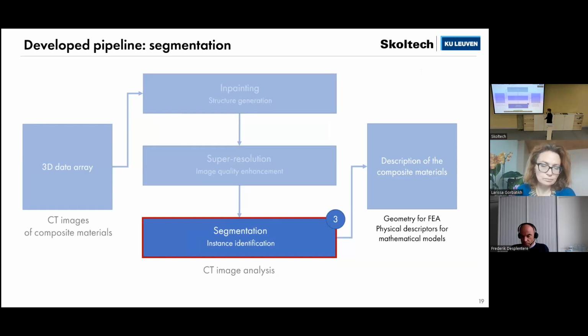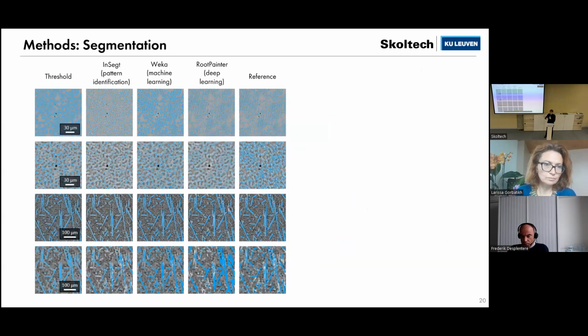The segmentation. The segmentation allows us to identify all the objects we want in our images, and here we analyze fibers. So we need to find all the fibers in our images. And here, in my PhD studies, I compared classical thresholding, pattern identification, and machine learning. Machine learning basically allows us to pre-calculate a lot of image-related metrics, and using these metrics, identify pixel by pixel segmentation. And deep learning already decides what metrics should be used on its own without our intervention.